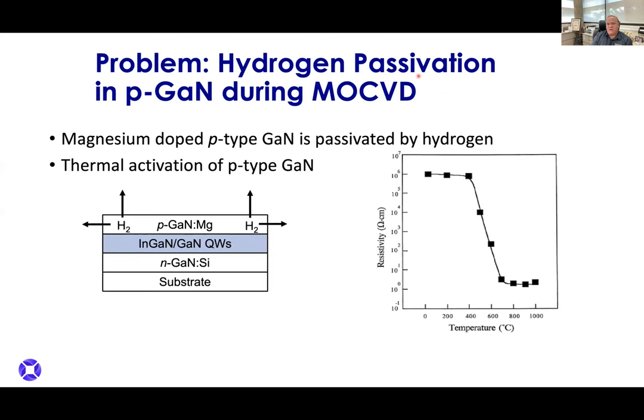But the problem was, when we tried to stack the LEDs on top of each other, the hydrogen needs to come out from the P-type. So one of the things Suji mentioned that got him the Nobel Prize was the fact that he figured out that hydrogen was passivating this magnesium atom here, and you had to thermally activate it in an environment without hydrogen around. And if you did that at temperatures above 600 degrees Celsius, you could see the resistivity dropped six orders of magnitude. So that's a million-fold change in resistance. So this is highly resistive, but this is low resistivity. And this got him the Nobel Prize.